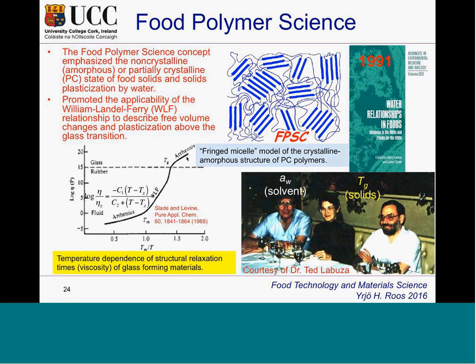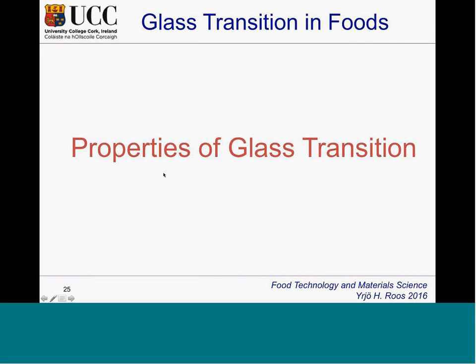So they published a number of publications, but the idea is shown here that if you are below the glass transition state, you have Arrhenius, above the glass transition WLF, and far away from the glass transition, you again have Arrhenius temperature dependence of phenomena. So around the glass transition, you have very rapid changes in kinetics, or also properties of materials.